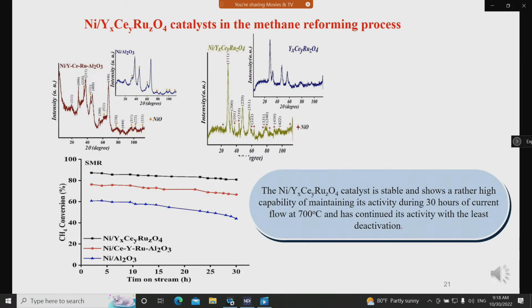Now, I want to show some examples using nickel perovskite for other reactions. In this slide, we applied a nickel yttrium cerium ruthenium oxide perovskite catalyst in the methane reforming process. As you can see from the XRD patterns, the catalyst was well prepared, and it is very stable and shows a rather high capability of maintaining its activity during 30 hours at 700 degrees Celsius, continuing its activity with the least deactivation.